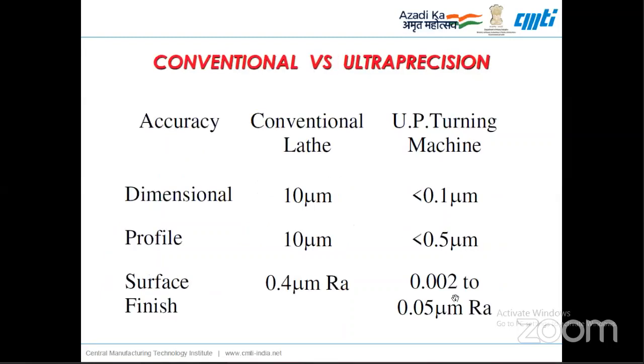Okay, and accuracy aspects. When we compare, in a normal lathe you can get a dimensional accuracy down to 10 micron and profile accuracy down to 10 micron on components. But in the diamond turning process, you can get down to 0.1 micron or 0.5 micron profile accuracies. And for surface finish, the best you can get on a normal lathe is in the order of 0.4 micron. But in ultra precision diamond turning, you can get down to 2 nanometers or even better in certain materials, and up to a maximum of 50 nanometers surface finish.